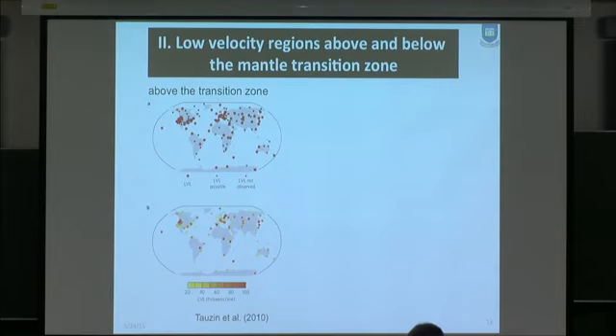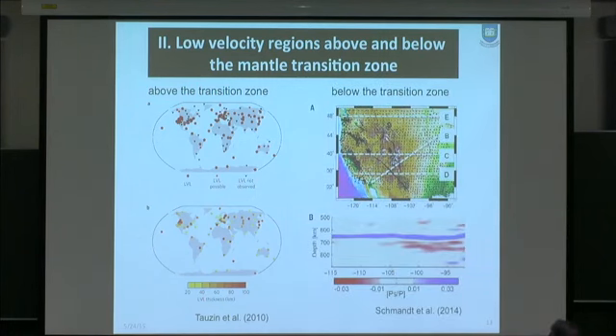There are some other observations in the deep mantle. One is the report by Tauzin et al., published about 5 years ago, showing evidence of low velocity regions above 410, which is nearly global. Those are body wave studies, those cannot cover completely global areas, but as far as they investigated, in the majority of regions they have some evidence of the low velocity layer, just above 410 kilometers. And there is also a recent paper by Schmandt et al. showing evidence of a low velocity region below 660, not 660, but 730 kilometers or so. And those are, as I said earlier, the plausible regions where melting might occur, caused by transport of water-rich material from the transition zone.